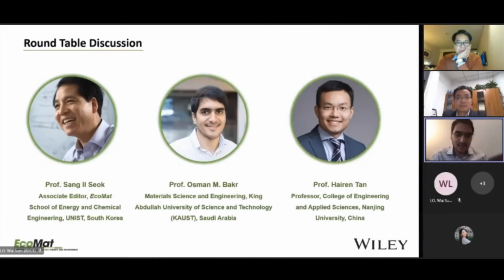So maybe I'll answer one more question, then I'll give the floor to Professor Tan. How do we test the EQE on a perovskite single crystal? Because it's small, we have to use a shadow mask. We have to make sure we're measuring the area very carefully. You can't rely on just the area of your electrode, because the diffusion length of the carrier is quite large, and it causes an overestimation of your effective current if you don't measure your area carefully and don't use masks to cover the area outside the device very well.